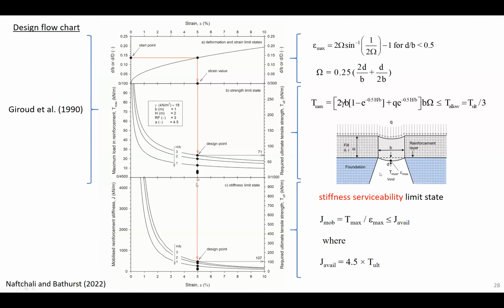Once you have established what the load is, you can then calculate what is the mobilized stiffness in the reinforcement. Because in order to sustain the maximum calculated strain and the maximum load, the material itself must have enough stiffness. So this is the stiffness limit state. And this has been a primary contribution of our work with respect to the problem of a reinforced fill over a void. So each reinforcement material has an available stiffness. We have just talked about that. And in order not to fail the stiffness limit state, the mobilized stiffness must not exceed this value.